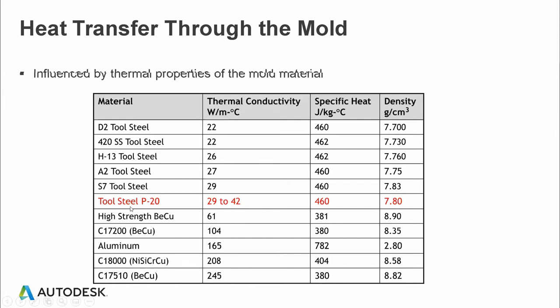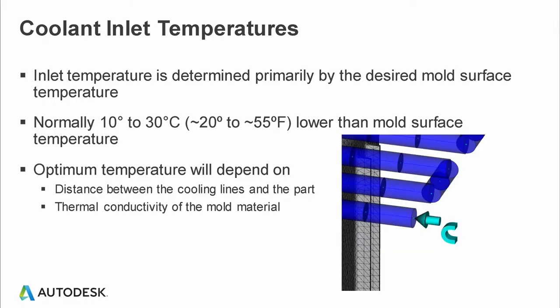Aluminum has a higher thermal conductivity compared to tool steel, but different grades of tool steel fall in the same range of thermal conductivity. Regarding coolant inlet temperature — this is a common question. Some people say the coolant temperature should be the same as the mold temperature, but that is not true. The coolant is used to maintain the mold temperature, and if the coolant and mold temperatures are the same, you won't be cooling the mold. The best practice is to have the coolant 10 to 30 degrees lower than the mold surface temperature.